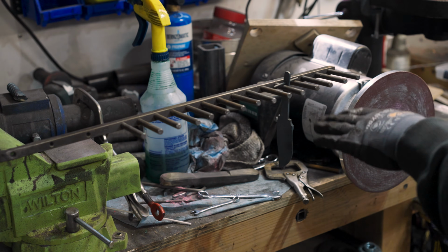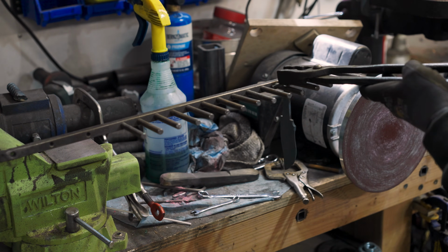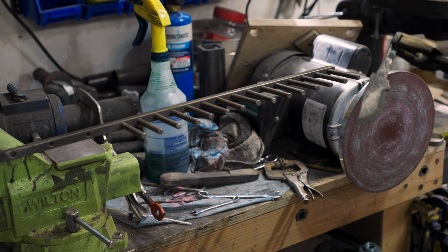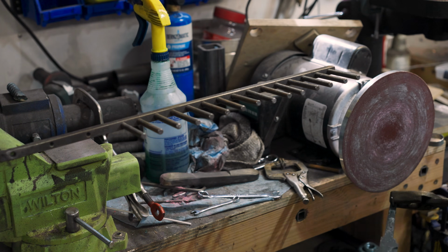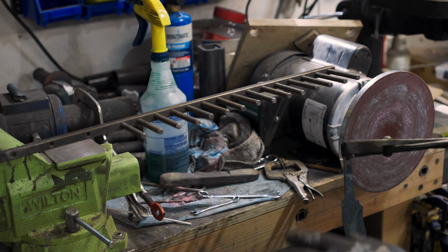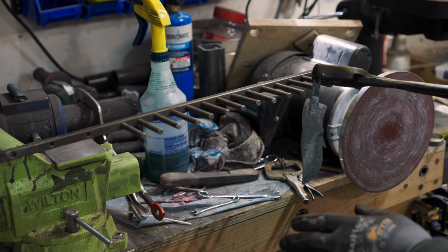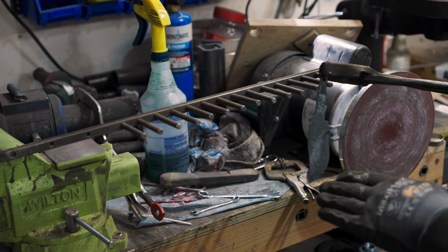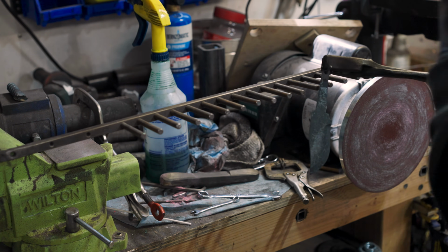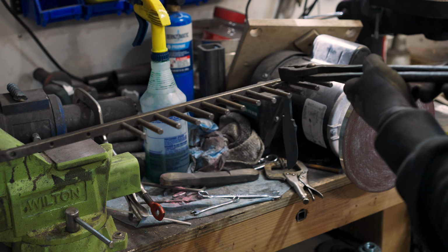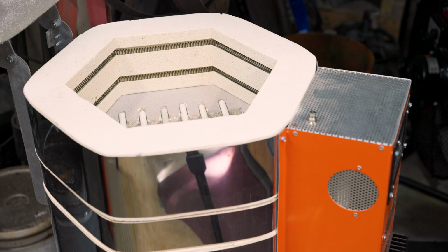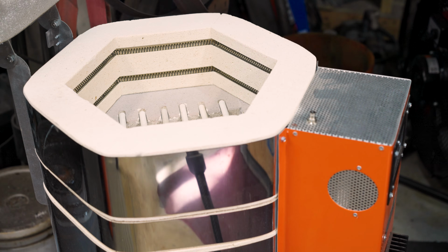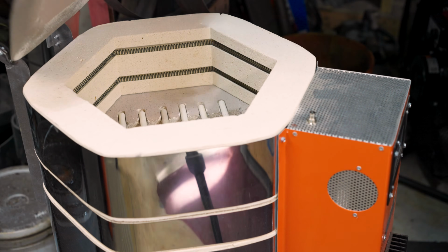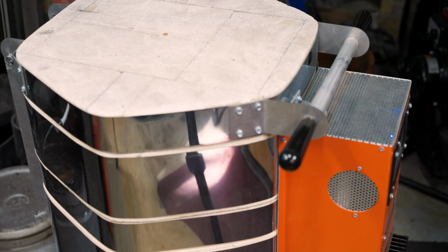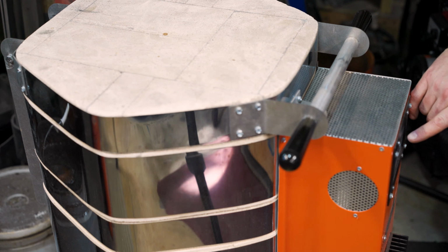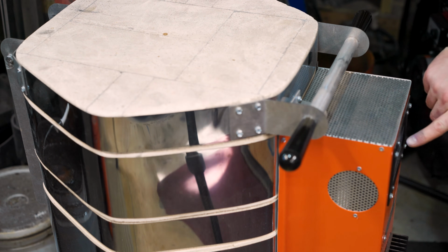So when this loses all of its color, what I typically do is I take this and I will put it in a shadow somewhere under my bench or wherever it's darker in the shop, and I'll make sure that all the color's gone from this, and then we'll throw it back in the kiln at 1500 degrees. So I'm leaving this lid open so that some of the heat can escape. And what I'm going to do is close the lid and then start my 1500 degree schedule.